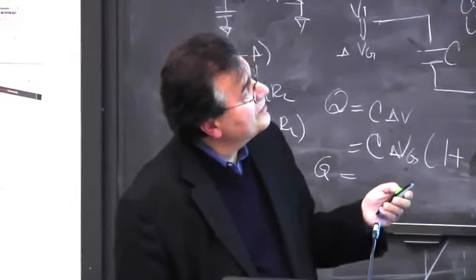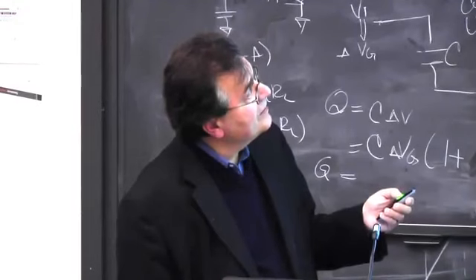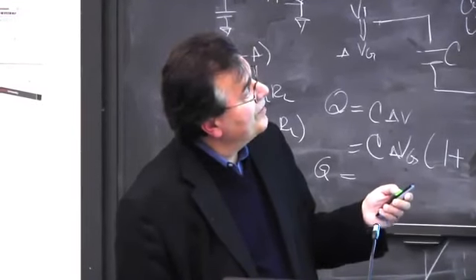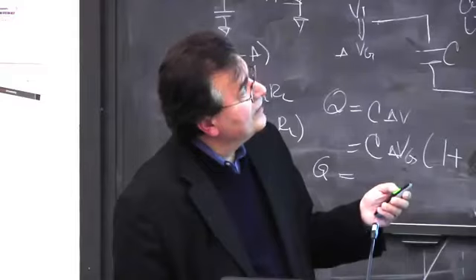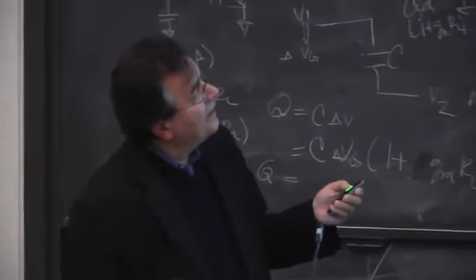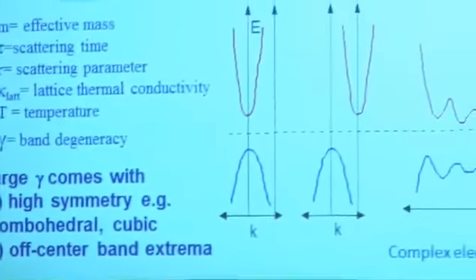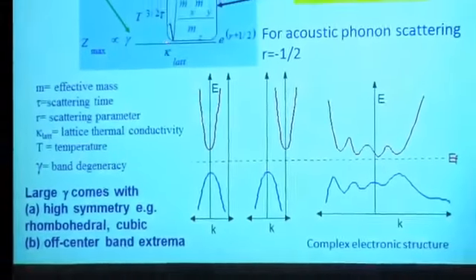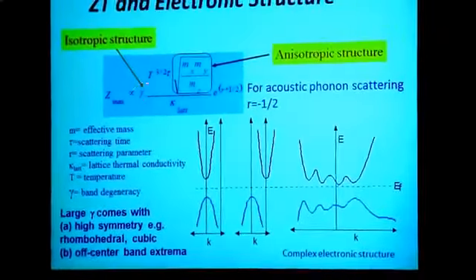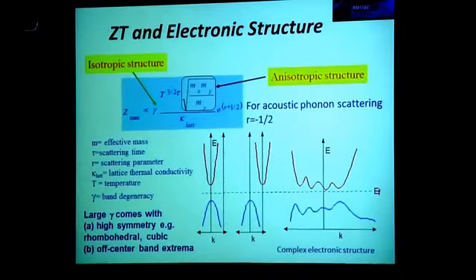You need a high anisotropy in the effective masses in this fashion. If the good direction, the flow direction, is the Z direction, then the effective mass along the Z direction should be small, and the others should be large. And of course, the lattice thermal conductivity going here. So, what does a large gamma mean?